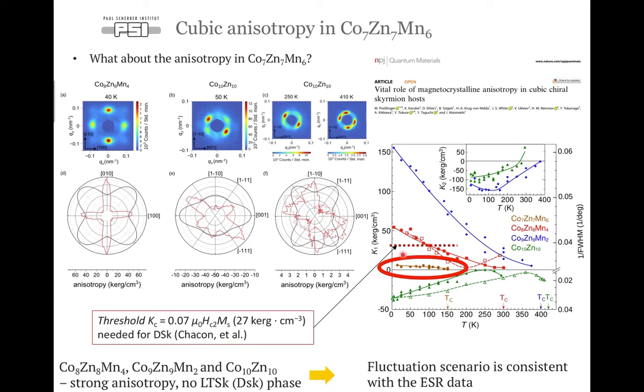with a lower manganese concentration. And we have calculated the threshold determined theoretically from the Nature Physics work for copper selenide that was discussed above. And actually, we have shown that the anisotropy constant is well below the theoretically proposed limit for the low temperature Skyrmion phase. Therefore, we need an additional mechanism that stabilizes Skyrmions at low temperature. The magnetocrystalline anisotropy is not the one that can explain the occurrence of the additional Skyrmion phase in cobalt zinc manganese 776.